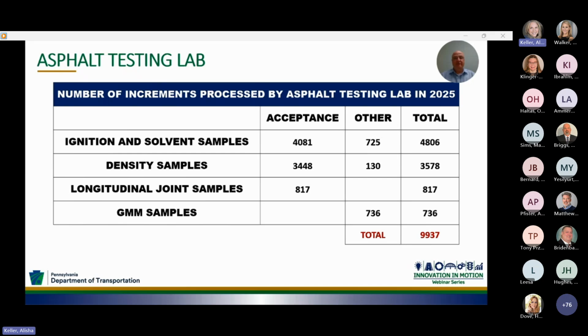In 2025, the Asphalt Testing Lab processed a total of 9,937 samples. As you see on this slide, the majority of these samples were acceptance samples. We tested a total of 4,806 ignition oven and solvent extraction samples, 3,578 density samples, 817 longitudinal joint samples, and 736 GMM samples. Processing such a large volume of samples requires a tremendous amount of effort and teamwork, and our technicians work around the clock to ensure that these samples are processed in a timely manner.